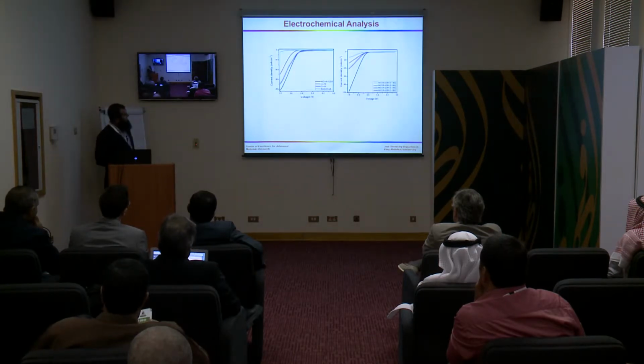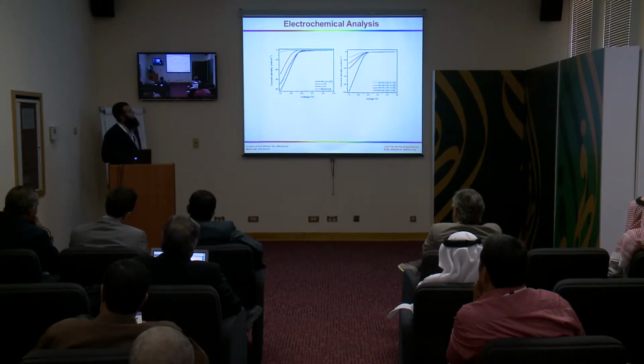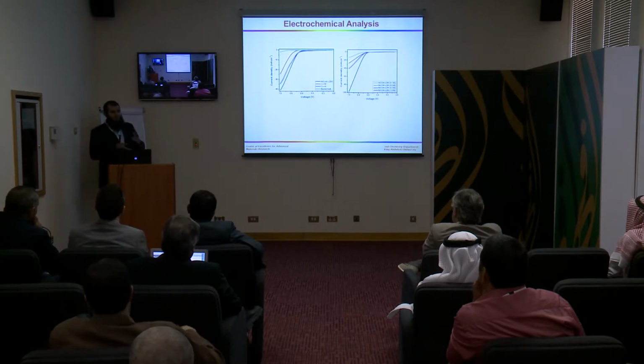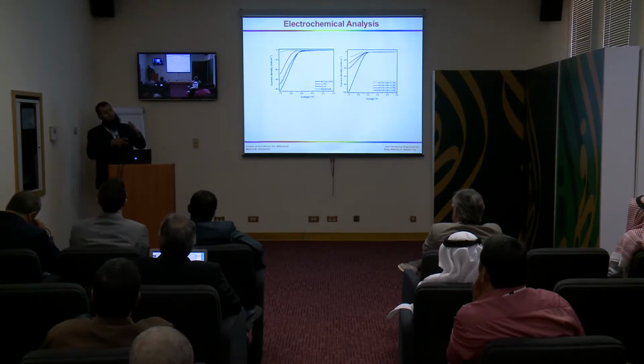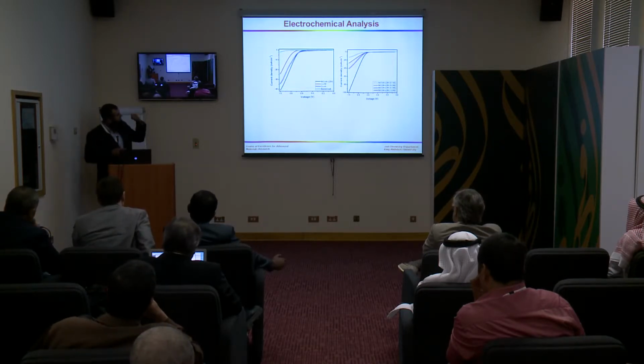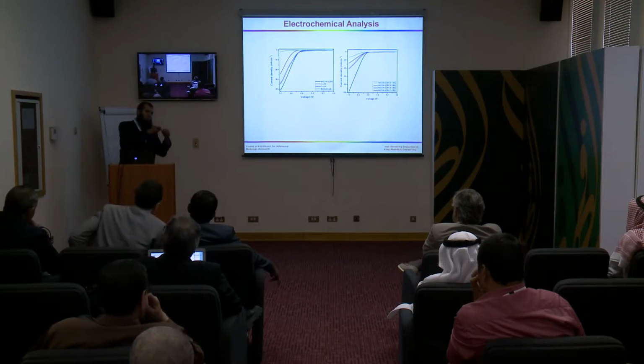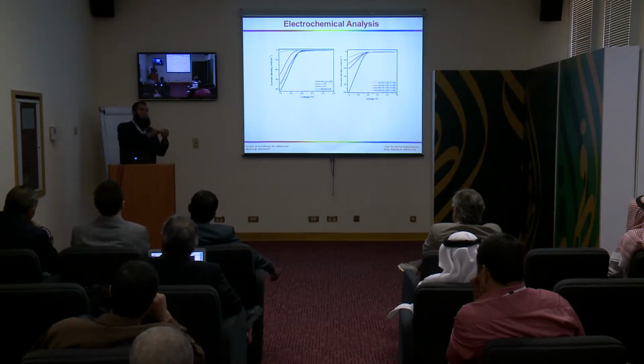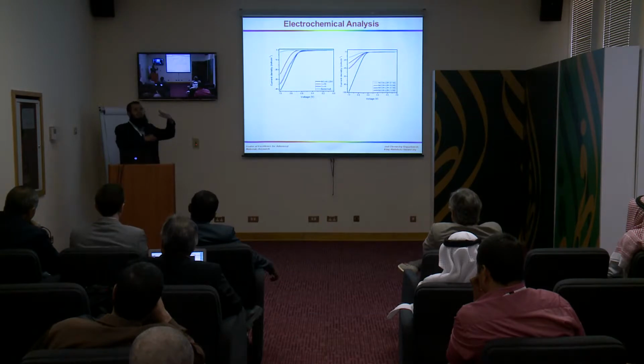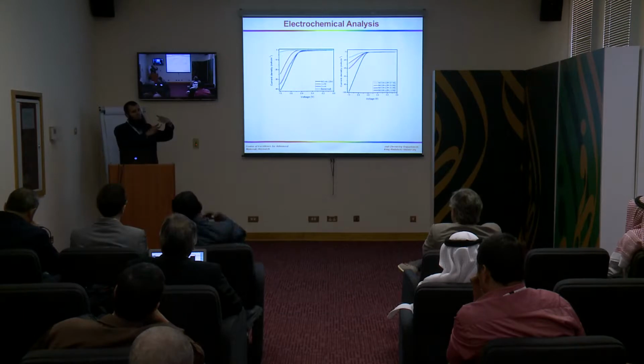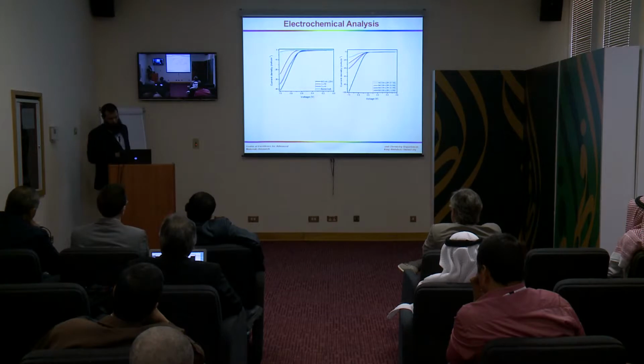And when we applied it to water splitting, the LDH showed high current density even at lower potential. According to our speculation, the LDH has a layer structure, and inside the layer there is carbonate ion. When we use this material as the anodic material, the OH ion comes in because of the layer structure. The layer structure of the LDH has positive charge, and maybe the OH ion comes very frequently. That's why it shows higher current density at lower potential.